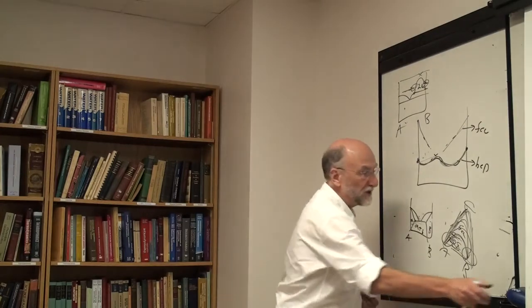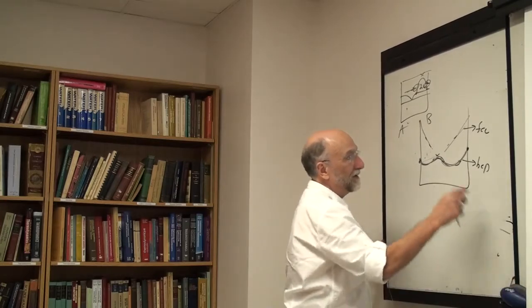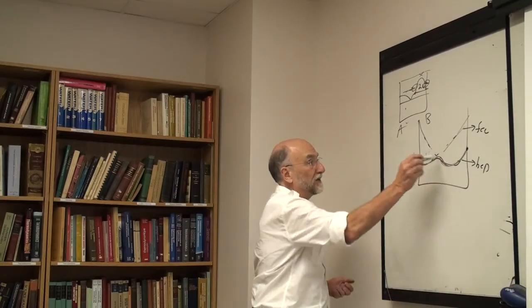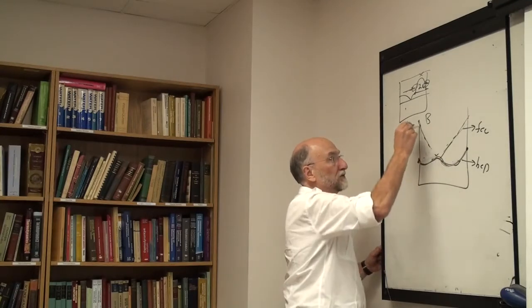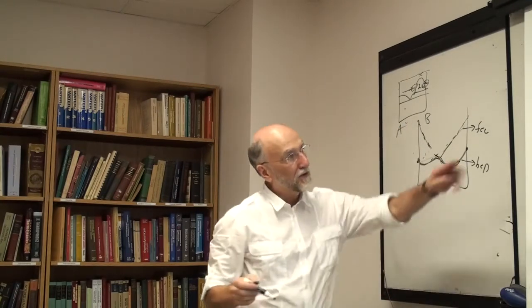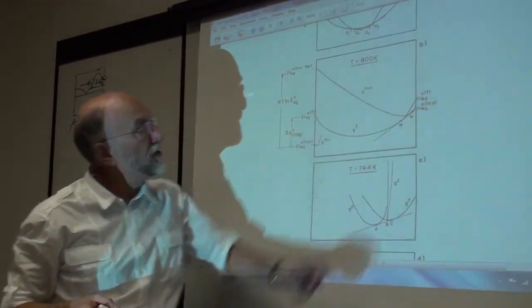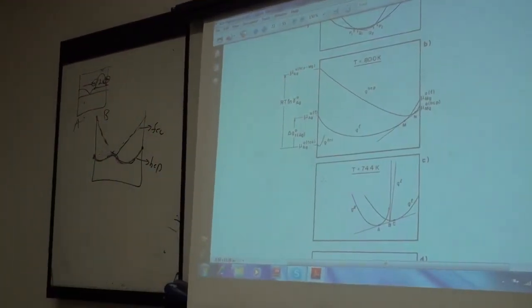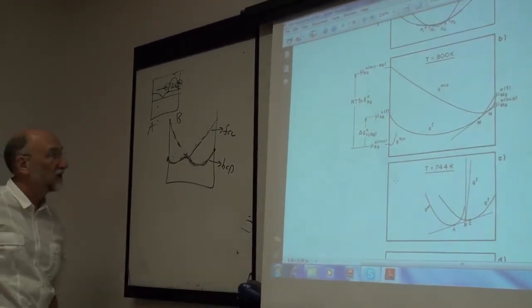So when the two systems have the same structure, which is of course always the case in a liquid, and in the case of a solid can be the case if they have the same crystal structure, then in principle we're not really supposed to fit them up this way with one equation here and another equation in the other phase, because then there's always a two-phase region. You can never at any temperature or composition ever get a single phase at all compositions.